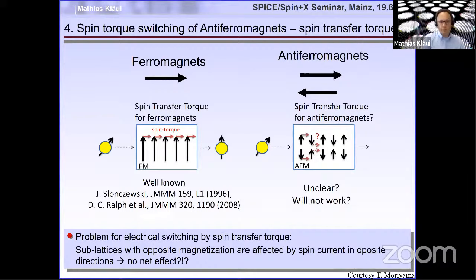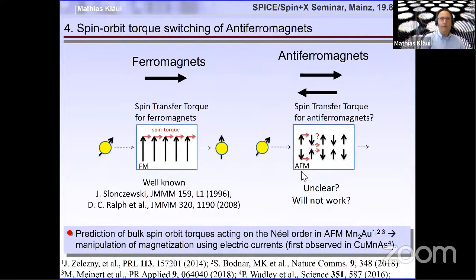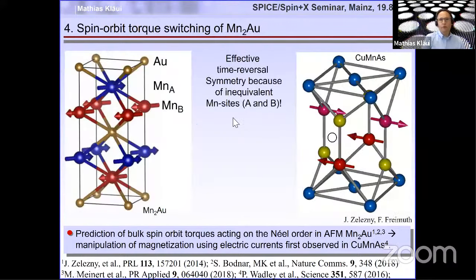One needs to think a little bit or talk to a smart theoretician like Helen Gomonay. Actually, it turns out that what you really need is a torque that is different, acting on the two sublattices. And this really exists. This was first observed in copper manganese arsenide and then later in manganese two gold. And the reason is that these sublattices in manganese two gold and copper manganese arsenide are not equivalent.